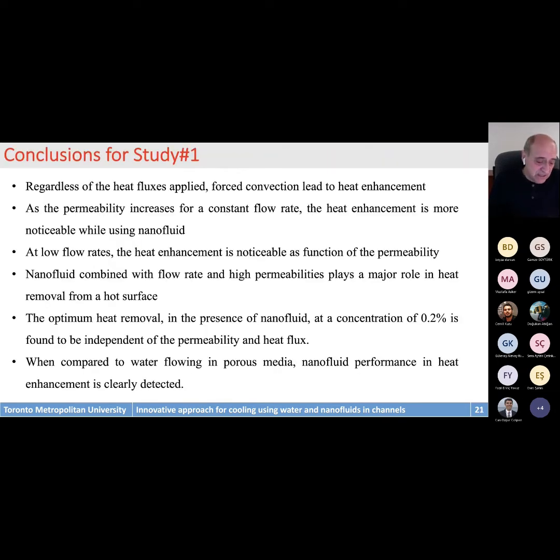We have published this finding in the Journal of Porous Media and other journals. So basically, the message I would like to convey for this particular exercise is that when you do experiments, nanoparticles tend to sediment inside the pores, so it must be checked that the porous media is always clear of obstacles. 0.2% for us performed better than 0.3 and 0.4, which is actually good, because it will reduce the pressure drop, and on the other hand, it will reduce any sedimentation or blockage in your channel or in your porous media.